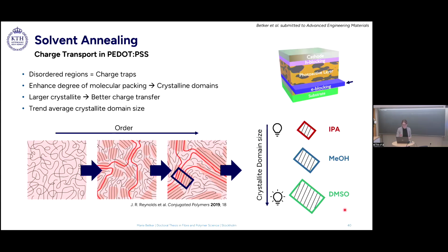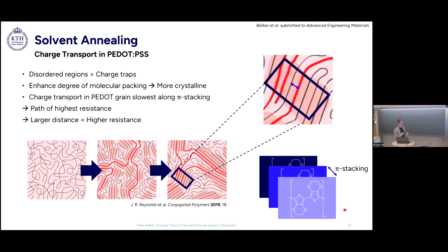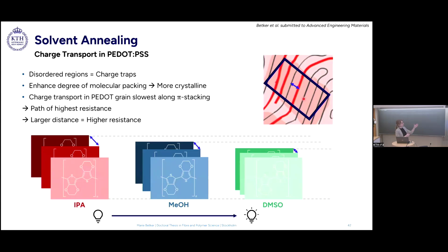And then finally, the limiting factor of such a polymer system is actually the distance between the polymer chains, this distance here. And we call this pi stacking. The larger this distance is, the tougher it is for the charge to travel, so less conductive. So to put it together, we want small distance, so easy charge transfer. And again, we tested that for the 3 different solvents, and it correlates very well with the results. So for the isopropanol, we found the largest distances, while for methanol and DMSO, the distances decreased, which explains their higher conductivity.